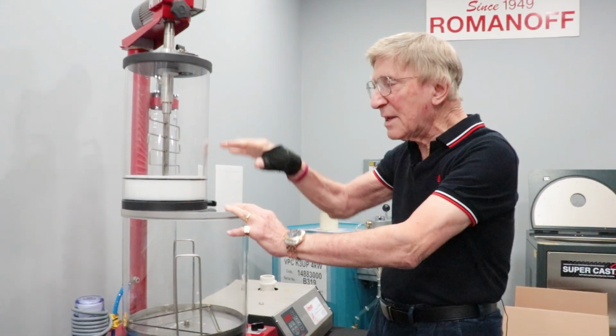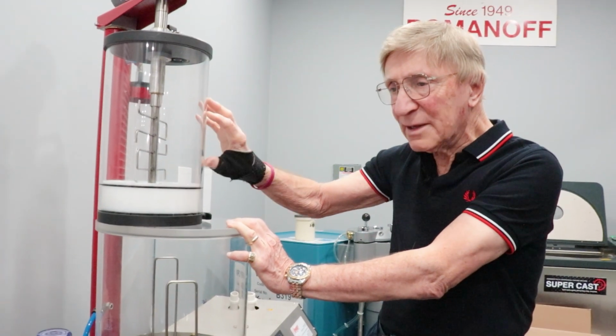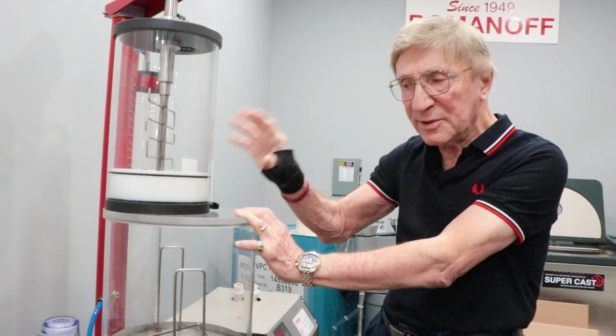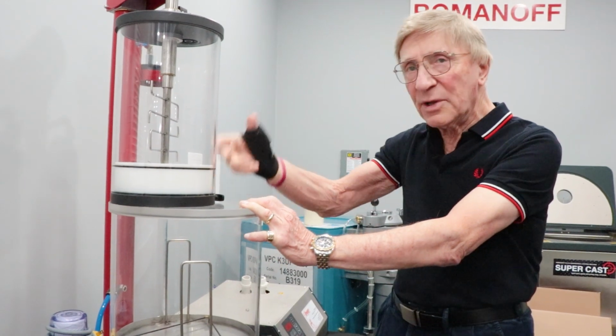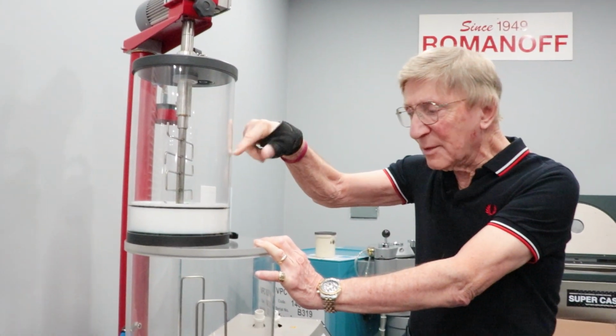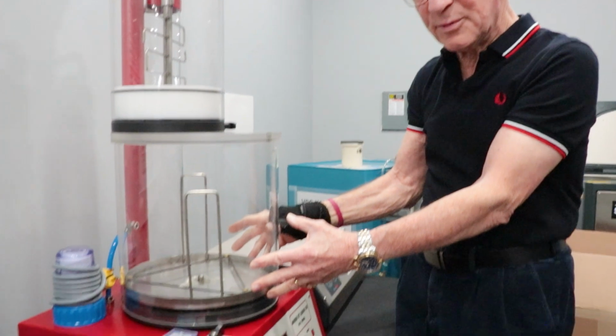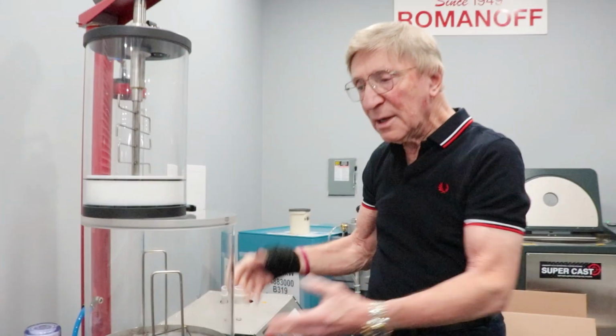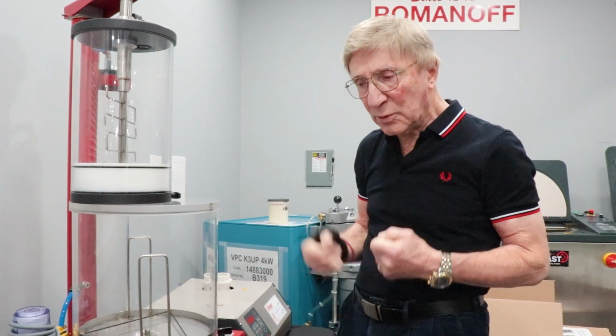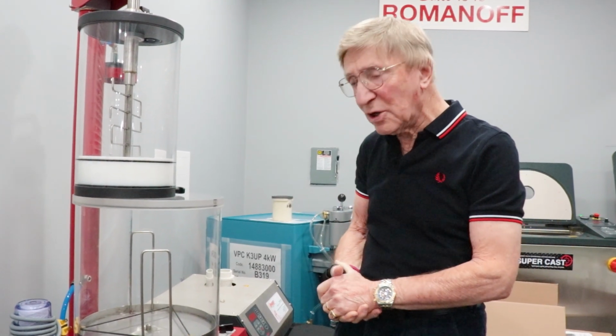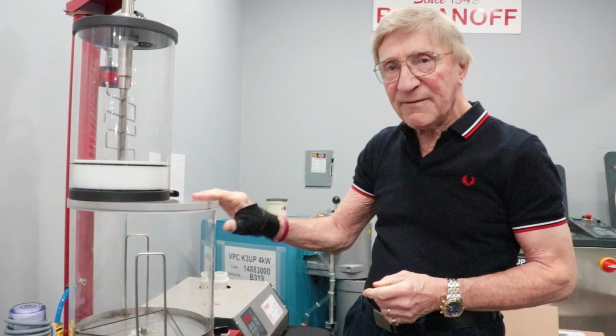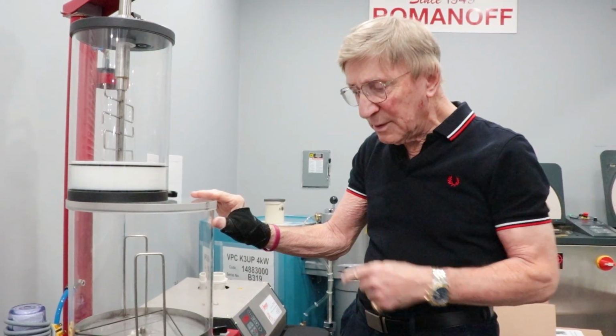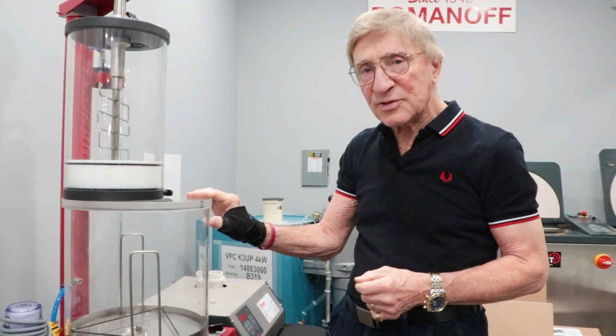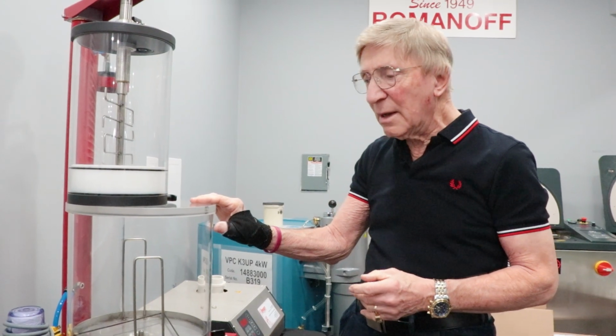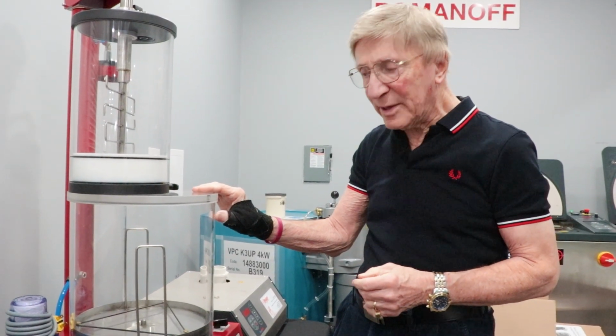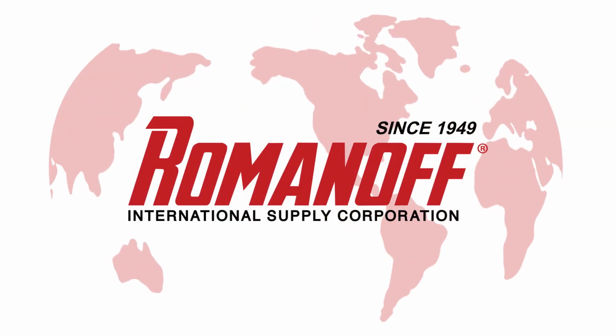And the benefit is that all this is taking place while it is under vacuum, so there is no chance of bubbles on the castings. You removed all the air from the investment while it's in the upper mixing chamber, and when the investment goes into each individual flask, the air is being removed from it. So once again, there are no bubbles on your castings, which helps the quality of the casting. And also by vacuuming the investment during the mixing procedure, you're also making it much smoother and more homogeneous, so the surface of the castings will be better when it's done in this process.